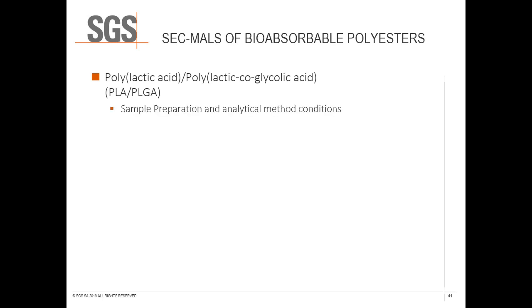The PLA configuration present in these samples allowed adequate dissolution in tetrahydrofuran. Because we had information from the client expecting the samples to be of relatively low molar mass, the samples were prepared at 5 milligrams per milliliter, a higher concentration than we would typically use for SEC-MALS. The higher concentration is necessary for low molar mass samples because the light scattering intensity is related to both molar mass and concentration. In order to obtain adequate light scattering signal for lower molar mass samples, you must increase concentration.